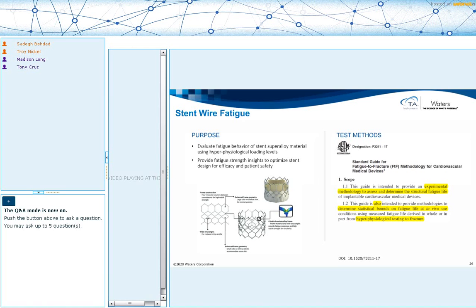A lot of times, shape memory alloys are used to make these stents, and we'll discuss why. But what is really interesting here in this example, this study is one of the landmarks that was done a few years back. And we are looking at two notions here. One is we are trying to test a sample under hyperphysiological conditions, meaning that we are testing the samples under conditions where you're pushing it above what it will do in the actual conditions to induce a failure. So that's why it's called a fatigue to fracture or fatigue to failure.